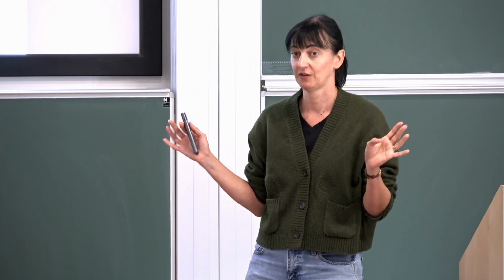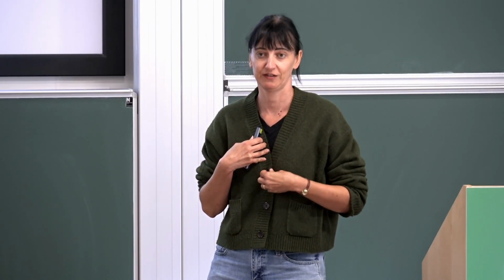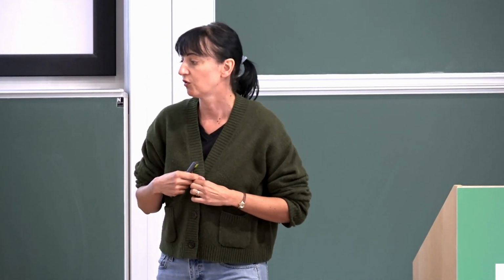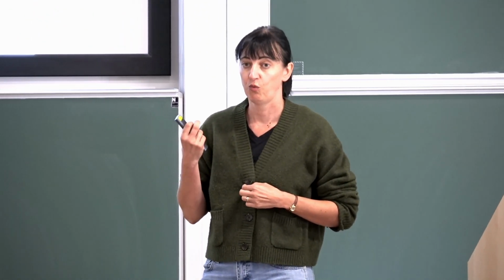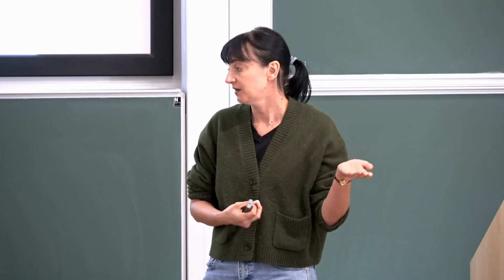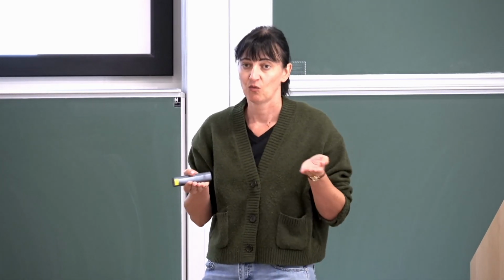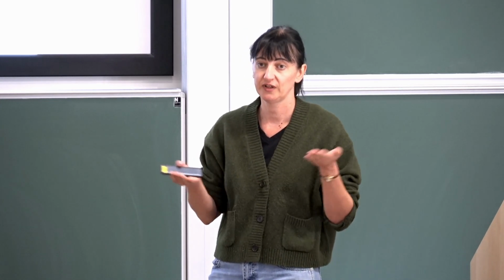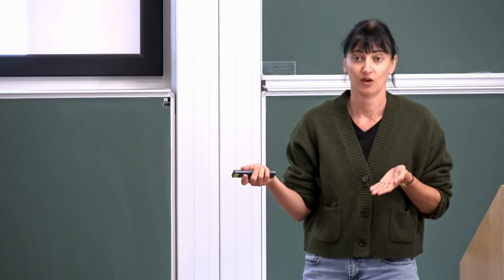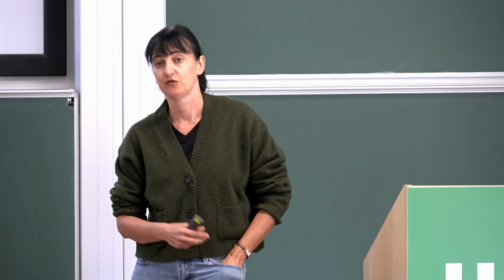and never experiment with model, despite the fact that this is what I was supposed to do in the first place as an experimentalist. And why is it the case? It is because you don't know your micromagnetic parameters precisely enough to be able to say anything in comparing an analytical model with an experiment. In fact, the only thing you can do is to fit one and another. And really, you don't learn anything, neither from the experimental point of view, nor for the modeling point of view. It's only really the comparison of simulation and models that helps you to understand.